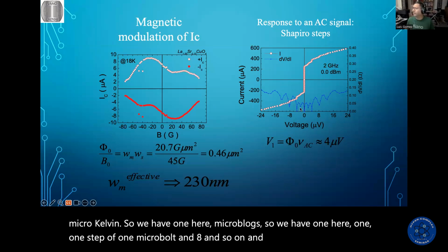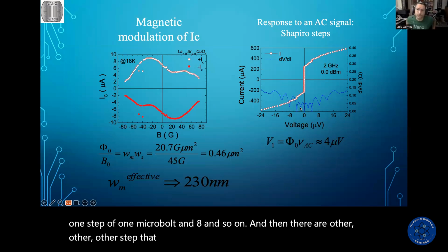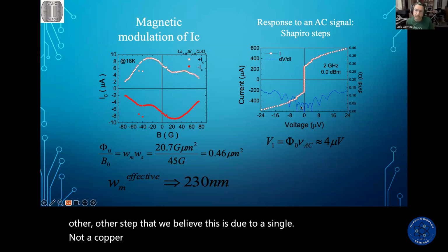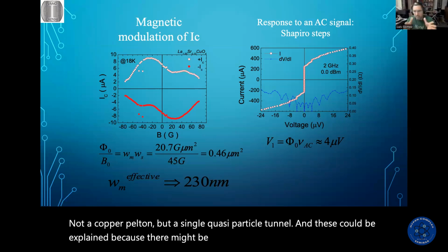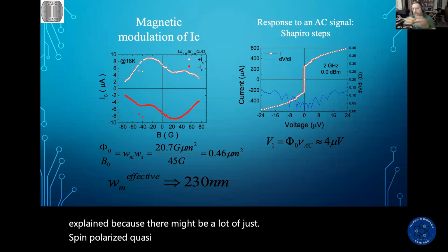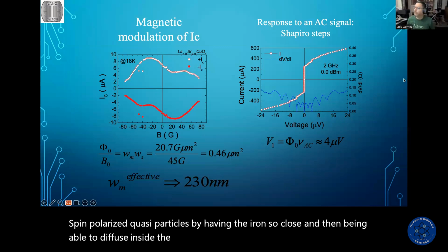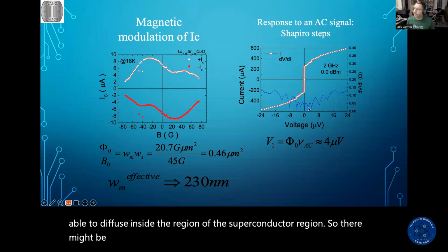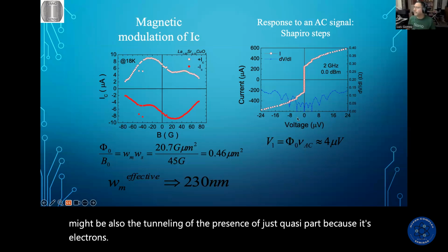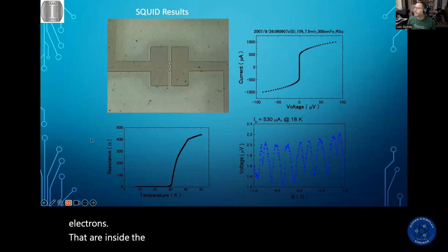And then there are other steps, but we believe this is due to single quasi-particle tunneling, not a Cooper pair tunneling. This can be explained because there might be spin polarized quasi-particles, due to the iron being so close, diffusing inside the region of the superconducting region. So there might also be the tunneling or presence of just quasi-particles, electrons, inside the junction.